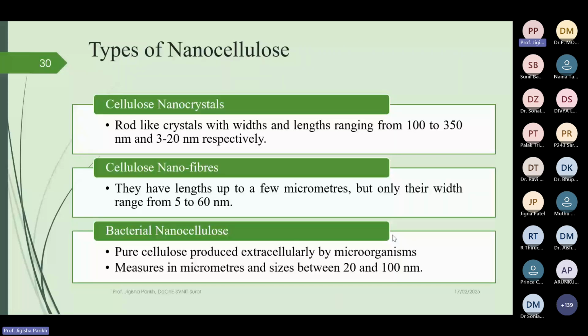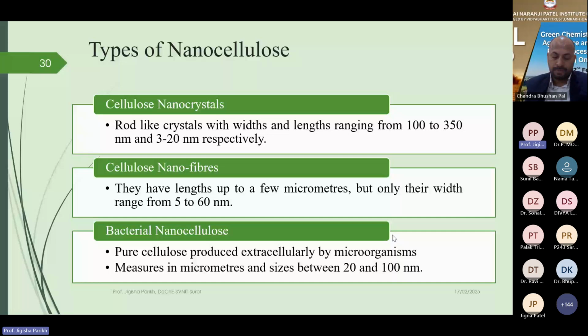Now, this nanocellulose, there are different types of nanocellulose. The major three types are placed here for your reference. So, cellulose nanocrystals are rod-like crystals with lengths and widths ranging from 100 to 350 nanometer and 3 to 20 nanometer respectively. Cellulose nanofibers have lengths up to a few micrometers, but their width ranges only from 5 to 60 nanometer. And there is the bacterial type of nanocellulose, which is produced extracellularly by microorganisms, and it measures in micrometers in length and 20 to 100 nanometer in size.